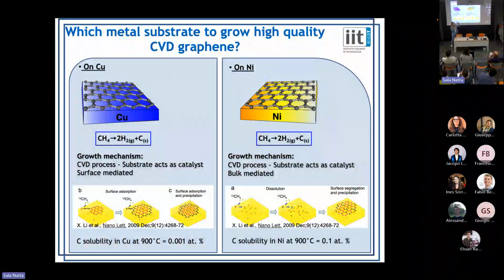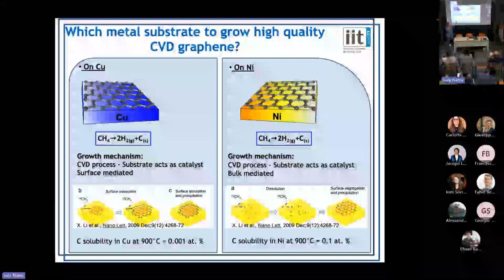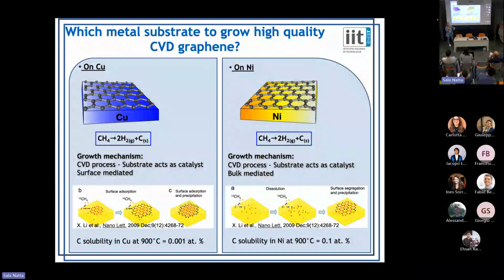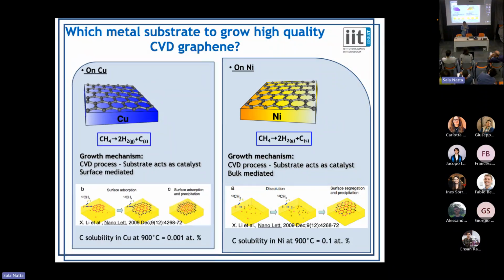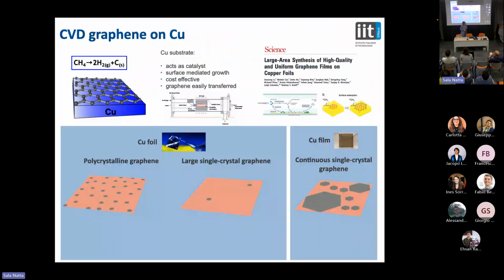And there you have problem to control the number of layers. Here you can have a monolayer, no problem, with a little bit of bilayer islands. There you can have 3, 4, really difficult to control the number of layers. And then it gets chaotic. So you don't have a continuous layer everywhere, where you have 2, where you have 3, where you have 4. It's very difficult to understand. So typically that's the one where we synthesize.